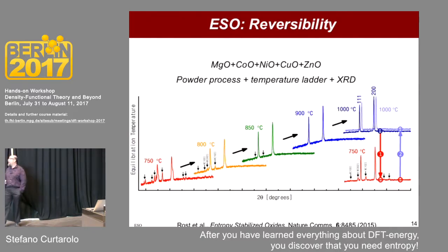Remember that another property of an entropy transition is that since it's based on temperature, disorder, it's like melting, right? If you go up, you melt, and if you go down, you solidify. And it can be reversible, you can do it as many times as you want. This transition is reversible. If you go up in temperature, you make them. If you go down, you go back to the previous fingerprints, these black lines. And you go up and down, up and down, up and down.